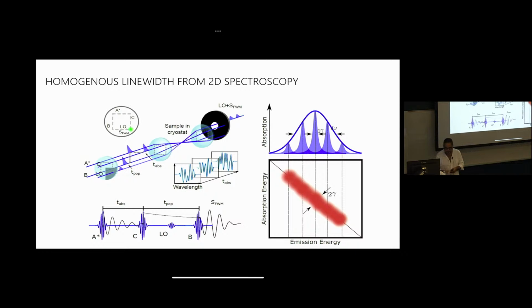To do that, we use another experiment that is a nonlinear optical spectroscopy, in which we're going to essentially measure something like a photon echo, but we're going to spectrally resolve it. So in this experiment, we bring in a sequence of femtosecond pulses in some well-defined geometry. Let's say we make a square and we put 4 pulses in the square. There's 3 of them that are going to produce the signal. There's another one here that is just an experimental trick to be able to measure both the amplitude and phase of the signal. But let me describe the experiment this way. And you really don't need to understand very much other than what I'm going to say at the very end of this explanation.